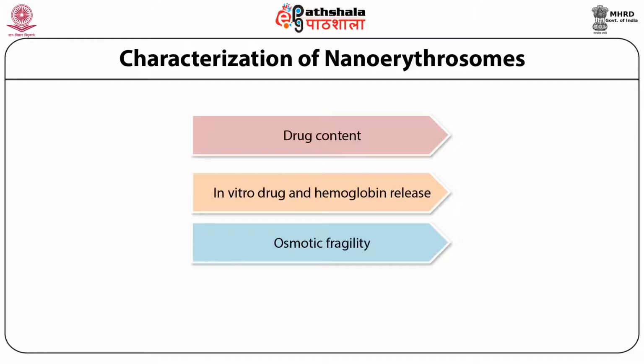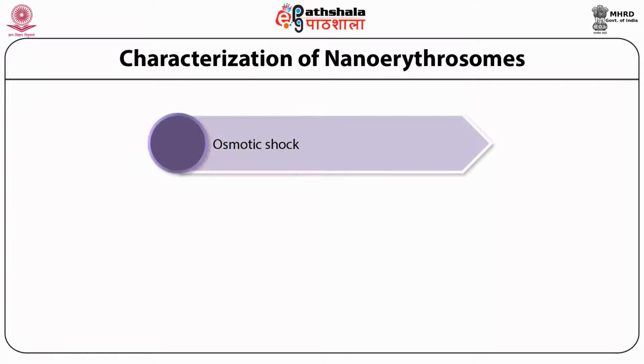Next parameter is osmotic shock. This entails an abrupt introduction of drug carrying red cells to an ambience which is beyond isotonic, to assess the capability of resealed erythrocytes to bear the stress and keep their integrity and form. Placing the resealed erythrocytes in distilled water for 15 minutes, followed by centrifugation at 1000 G for 15 minutes, can lead to liberation of hemoglobin to diverse extent, which might be determined using a spectrophotometer.